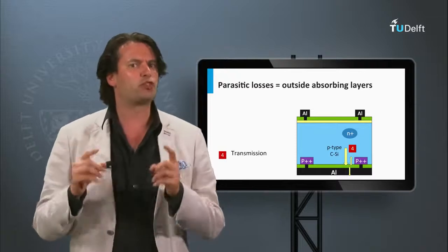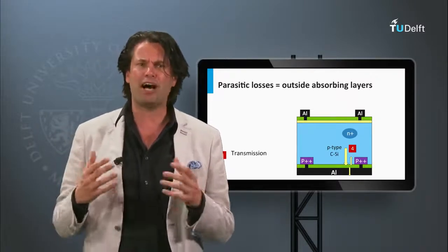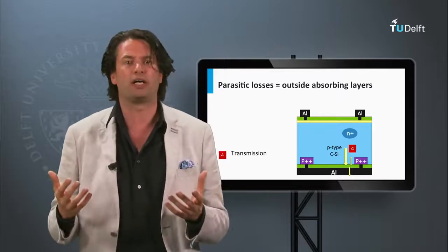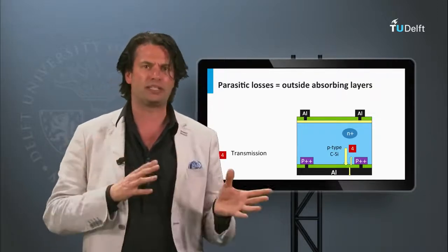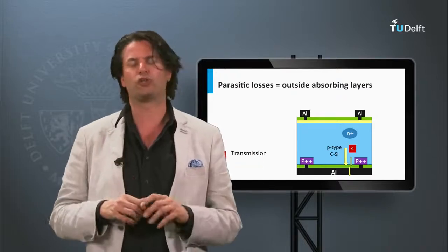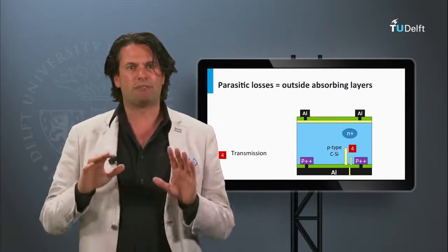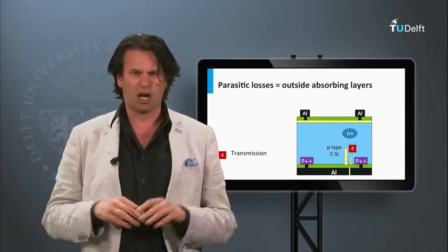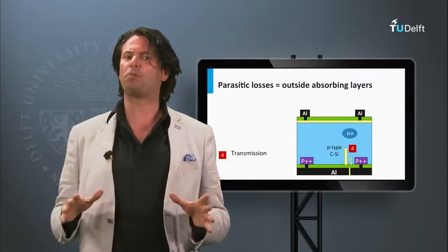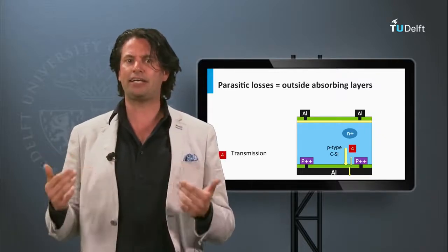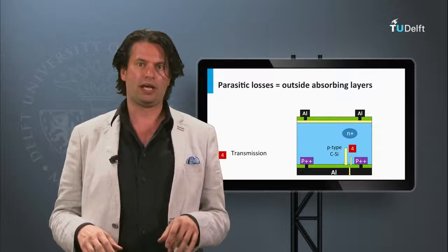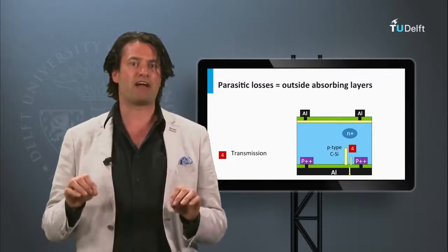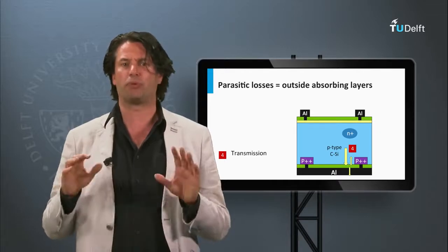Secondly, if the absorber layer is not thick enough to absorb all the light, part of the light will be transmitted. As the absorption coefficients are larger in the blue spectral part, this usually plays a role in the red to infrared part of the solar spectrum. The light transmitted can be reflected back, which is a so-called back reflector. Some of the light can also be absorbed at the back contact. This can again be considered as a parasitic absorption loss. In week 5, we will discuss thin film solar cells, where back reflectors and light scattering on the angles starts to play an important role.